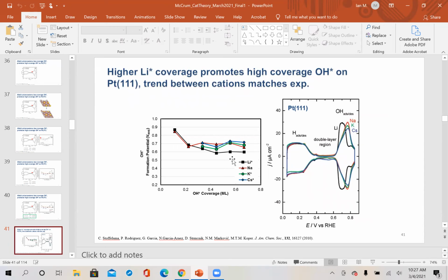So my guess would be it has to do with size in part, but I can't prove that. Can I just add something to that? I'm sorry. In thermal catalysis, looking at the effect of those, it is indeed a size thing, in the sense that you can't fit that many altogether. Your cesiums are larger, so you can't fit that many. That effectively leads to a difference in the work function change, perhaps a larger effective dipole overall. That's why I was asking originally whether this is just the same as thermal catalysis, just dipole effects really. Sure. Yeah, and in working through this, we've expected that there's some similarity with the promoting effects of cations in gas phase catalysis.